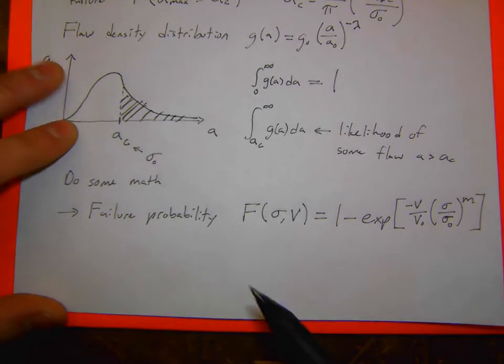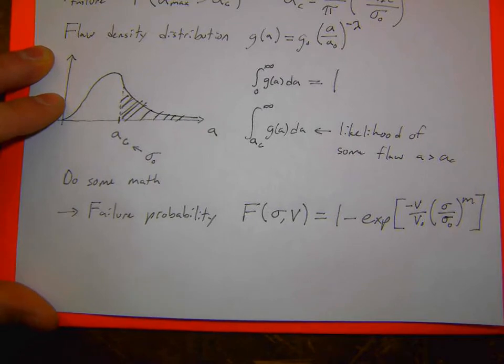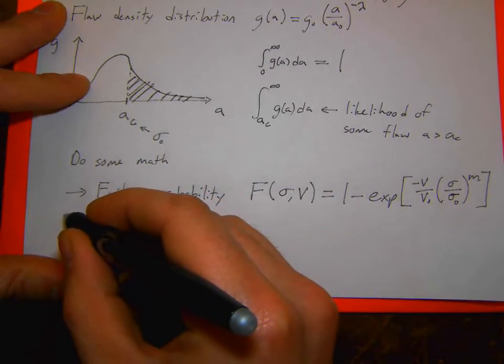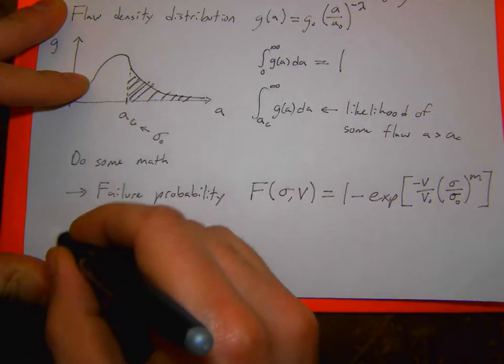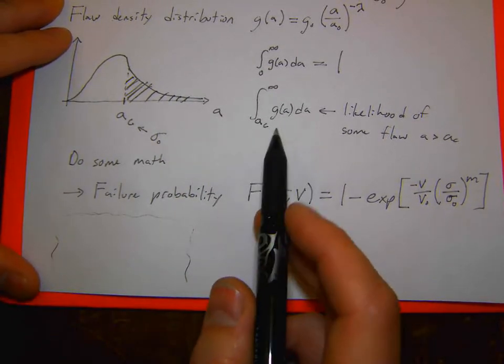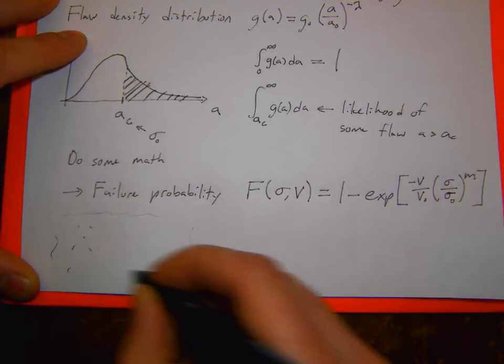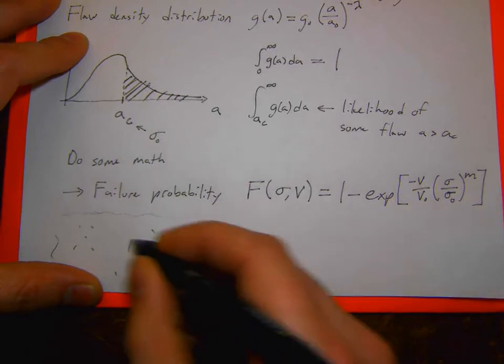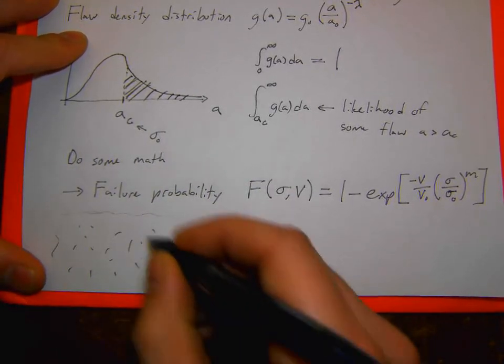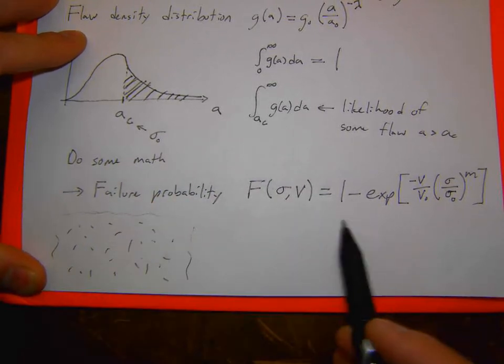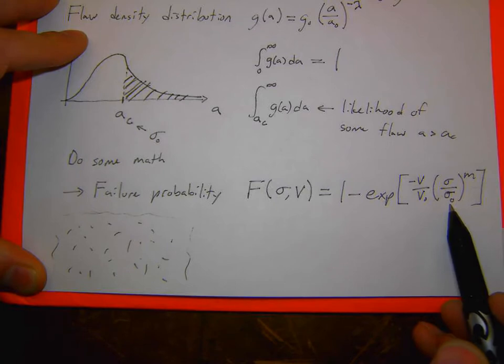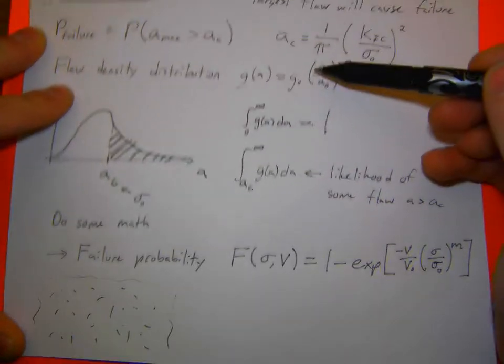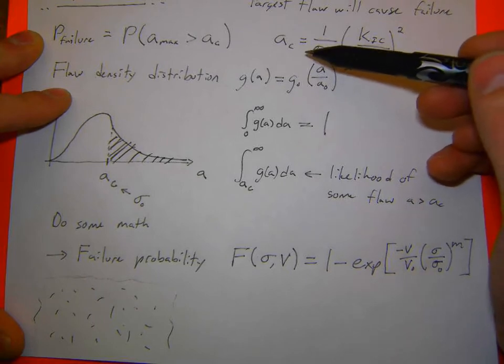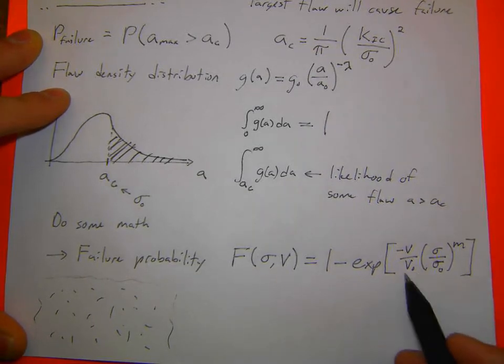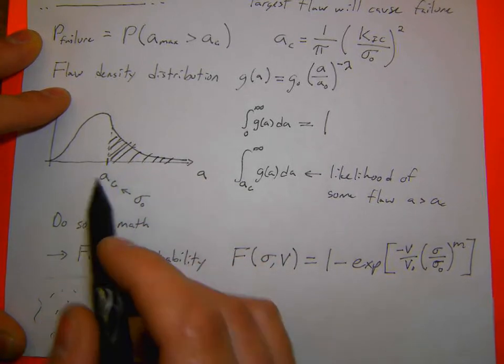The reason this pops up, I'm not actually going to go through the math, but I'm going to try to explain it qualitatively. Imagine I have some infinitely large part with the whole distribution of potential flaws. I have some very small flaws in this thing, some larger flaws. The probability of failure is going to be dependent on that applied stress, because that changes what the critical crack size is that I need for failure. But it's also going to be dependent on the volume of the part, because that changes the distribution of the flaws in this material.